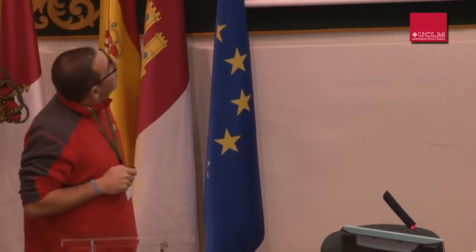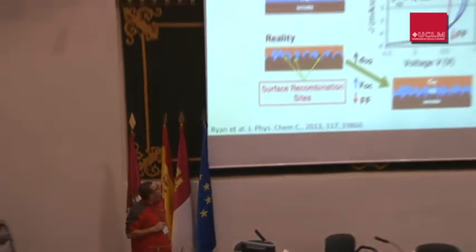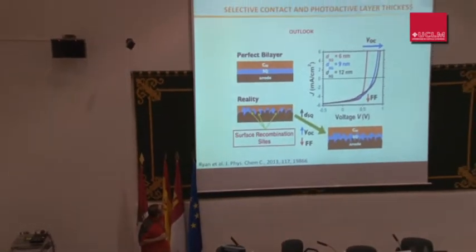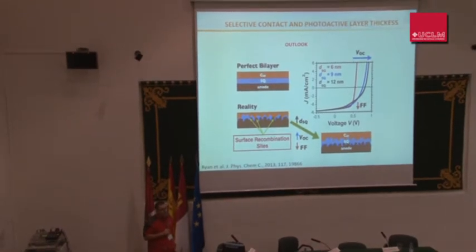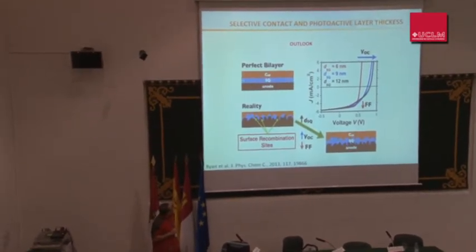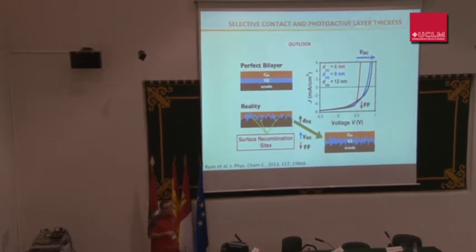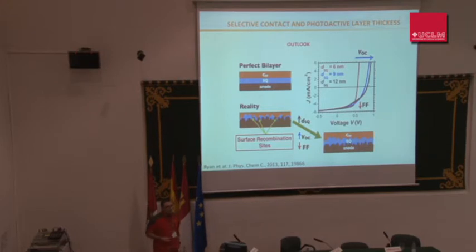So with this idea in mind, we did some experiments, and this is the classic picture you see in all papers from organic solar cells. This is the anode, which usually is ITO, indium tin oxide. And then people put a donor molecule, like a squaraine, and an acceptor molecule, and the only one which works very well is fullerene. But the reality is not that.